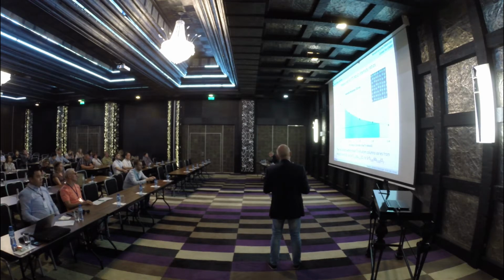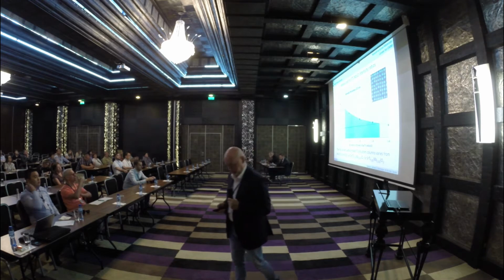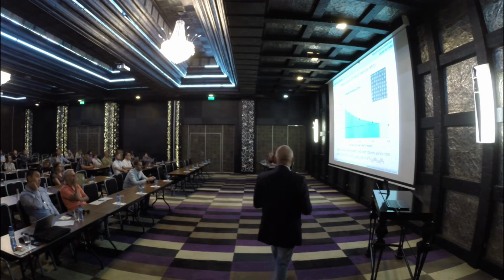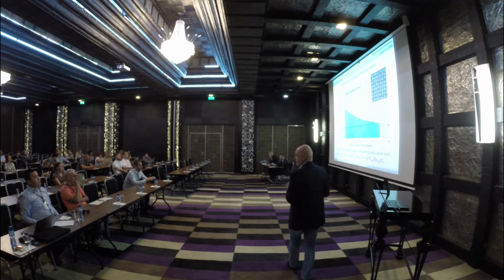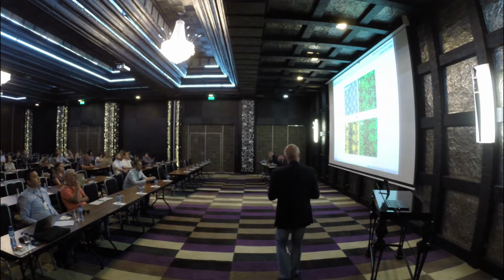We see that the titanium and niobium content, especially the niobium content on the B side, is varying somehow between 0.05 and 0.35 in this strontium titanium niobate. So this is important in order to retain electrical conductivity.